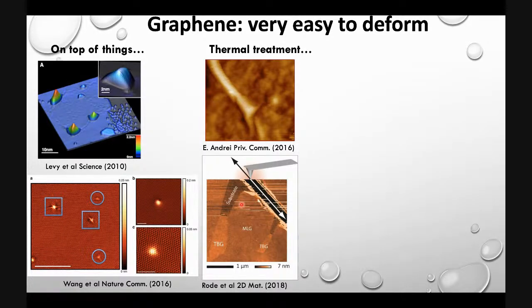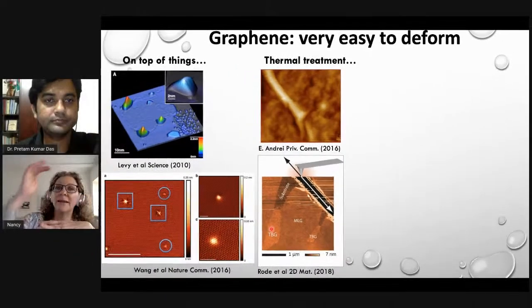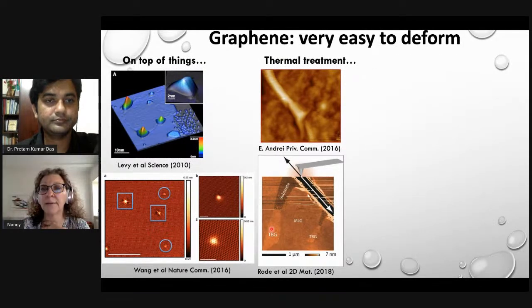It also happens when you scratch, like in this experiment, where the membrane was scratched with a very, very sharp tip that was creating a trench in the material, and instead of remaining flat or parallel to the surface, graphene automatically bends on itself and starts peeling off to create these ribbons that grow on itself because of the bending, the easiness of bending that the material has.